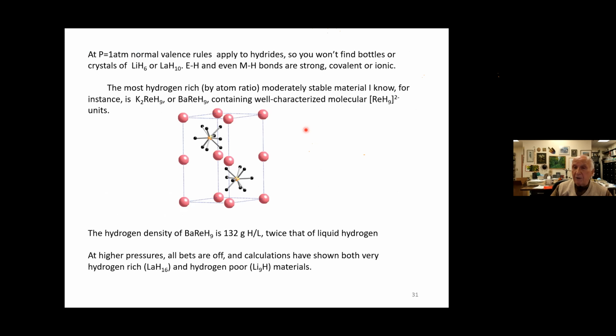At 1 atmosphere, normal valence rules apply to hydrides. You would not expect for lithium hydride anything else than LiH, because the valence of lithium is 1, and so is the valence of hydrogen. Well, there are some interesting modifications of that. You would not expect for calcium and hydrogen anything but CaH2. But it's clear that all the rules are off under high pressure. And it's interesting. Some of the things that you can get even at 1 atmosphere are interesting.